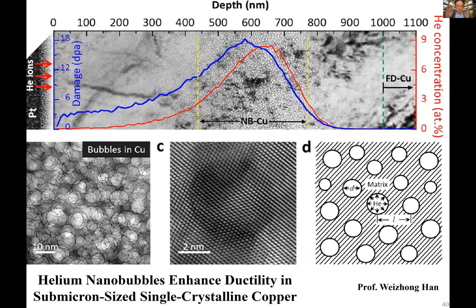With these kinds of models, we can also do direct mechanical property studies. A lot of my group's effort is on trying to come up with structural materials which are robust against radiation. And we found some pretty surprising effects. This is in collaboration with Professor Weizhong Han. He did work at Los Alamos, where he injected helium into single crystal copper. You see that where the peak helium deposition is, you get very big bubble porosity in the single crystal copper. And each bubble is just a few nanometers in size and very highly pressurized.